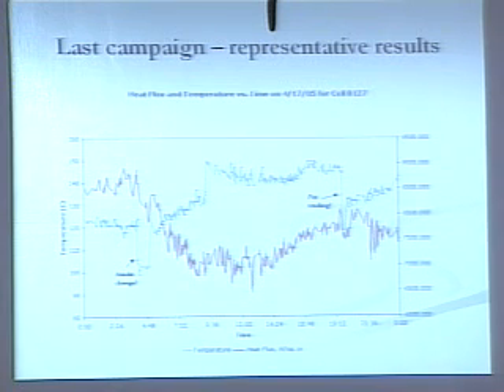Okay, so that's one piece of information which is valuable to the supervisors and to the people who worry about emissions from this plant. Now look what happens. The temperature starts to creep up. And the temperature starts to creep up because when they change the anodes, they damage this pie crust on the top of the molten salt electrolyte. And they're supposed to clean that up, fix it by putting fresh alumina around the hole. If they don't, the temperature in the gas stream gets up because now there's hot molten fluoride electrolyte in close contact with the air which is passing up and the gases which are passing up into the vent system.